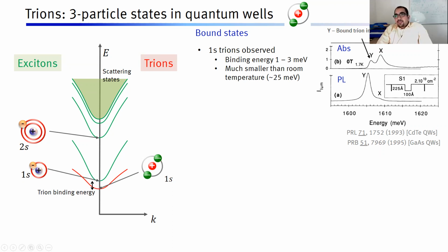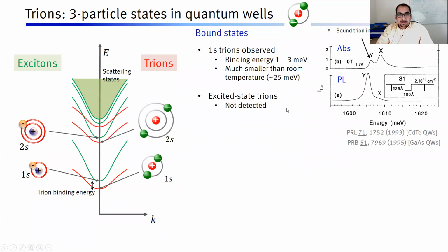Such trions were first observed in 1990s, actually, in cadmium telluride and gallium arsenide quantum wells. For example, in the absorption spectrum, you see a peak just below the exciton's peak, and this is a trion peak. This is absorption, and luminescence also you see a peak. The binding energy of these trions is very small, 1 to 3 meV. So you have to go to very low temperature. Here it's 1.7 Kelvin, because otherwise they will not be bound and you will not find them in the spectra. So this is much smaller than the room temperature.